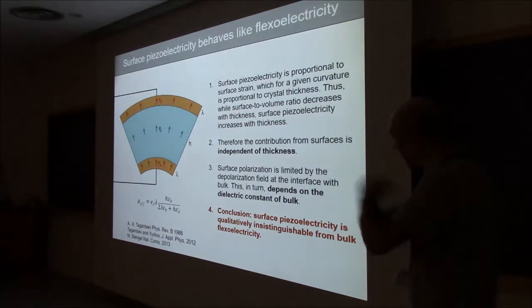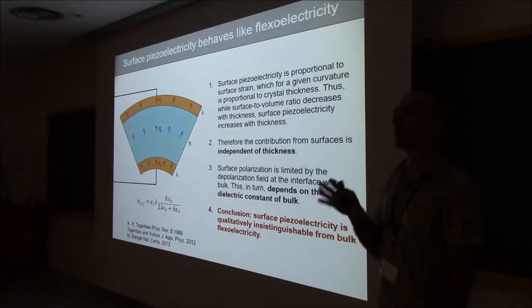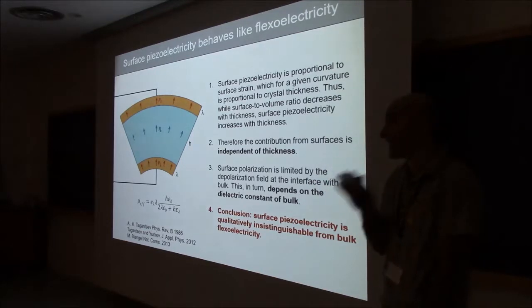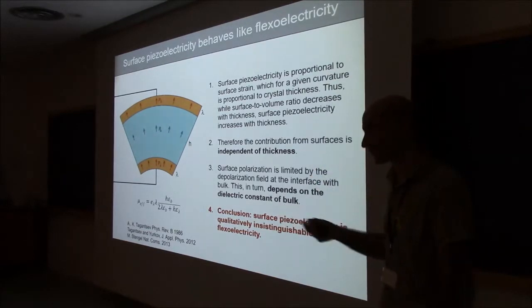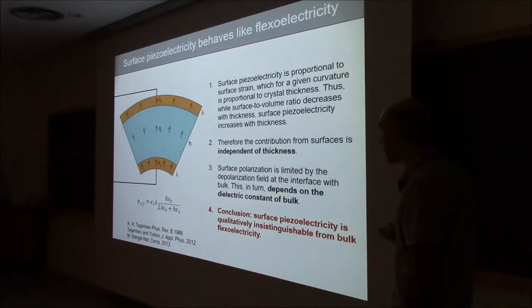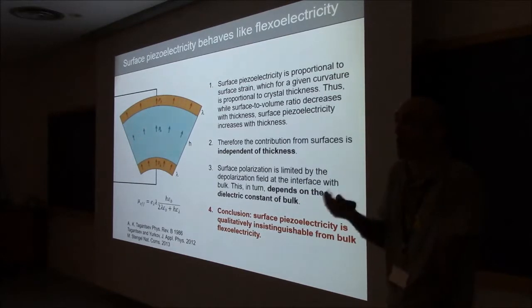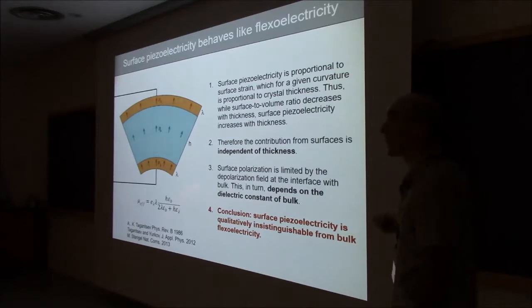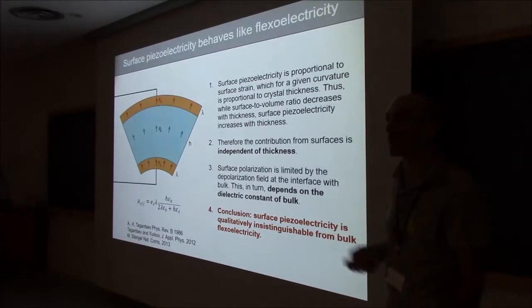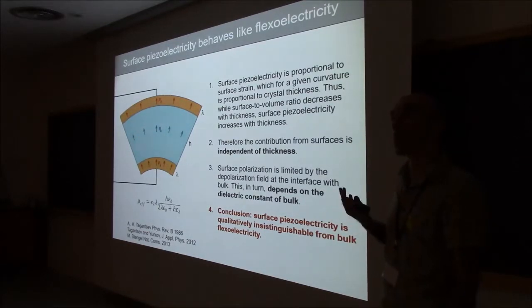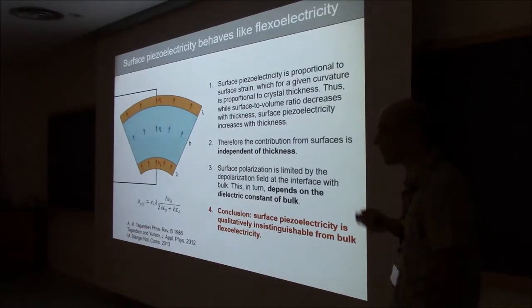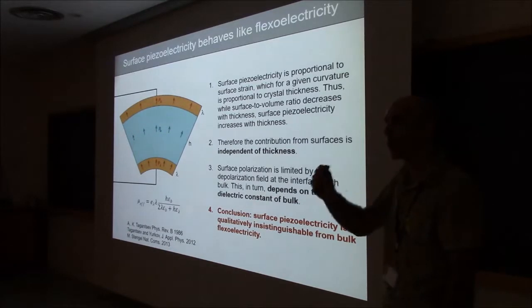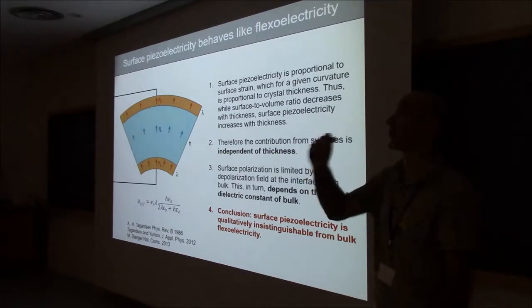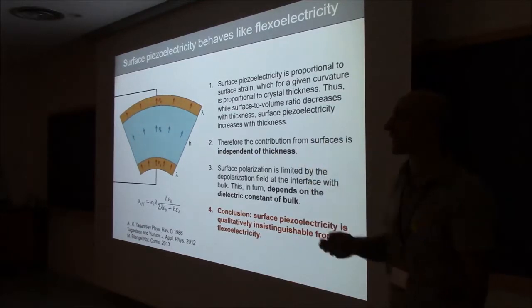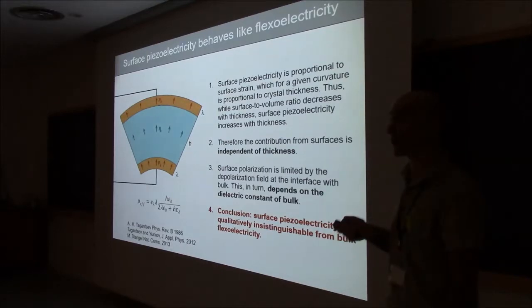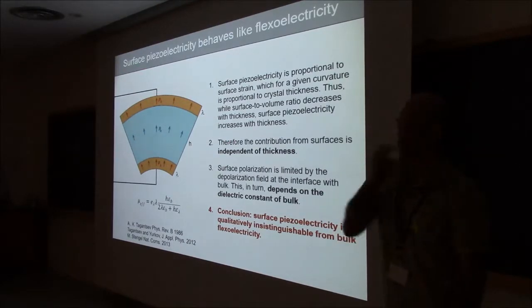So the conclusion of all of this is that surface piezoelectricity is qualitatively indistinguishable from bulk flexoelectricity. And again, it's a good argument to be made that since you cannot distinguish it even on a very fundamental level, maybe you shouldn't treat them as two different things. Max's belief is that basically they are two ingredients of the intrinsic flexoelectric coefficient. So the intrinsic flexoelectric coefficient has the intrinsic bulk contribution and the intrinsic surface contribution.